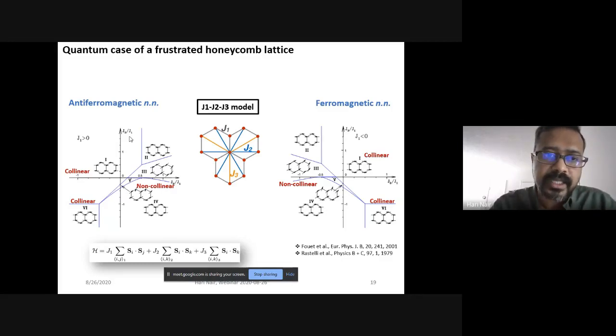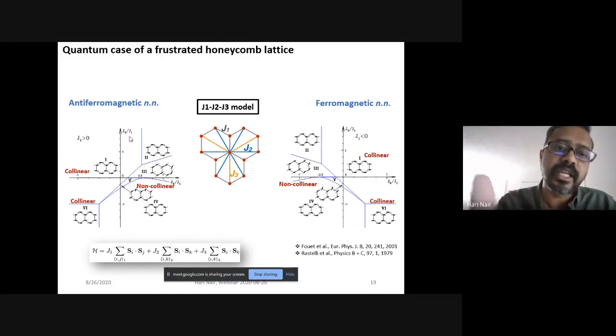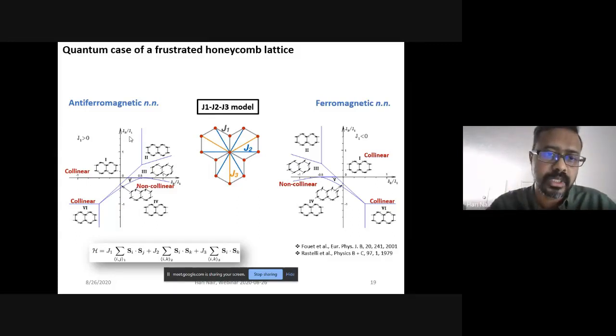Now, what is on the X and Y axis? The X and Y axis are nothing but J1, J2, and J3 normalized to J1 so that you can represent three numbers on a two-dimensional plane. It tells you that if I somehow tune J1 and J2, which is the interaction between the spins on the honeycomb, I can get different types of magnetic structures. And the thin blue line marks the boundary between different phases. So this is nothing but a phase diagram, very similar to the phase diagram of water, for example. And you would say that in one region you have ice, in one region you have everything coexisting, and in one region you have water and so on. Very similar here, just that you have different magnetic structures.